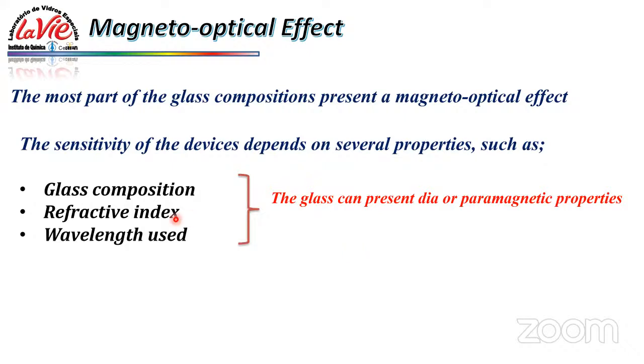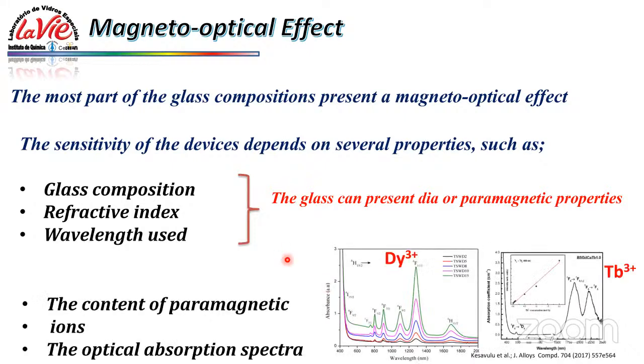We can also change the wavelength used, because the Verdet constant increases a lot with the refractive index. And how to do that? Usually when we work with glass, we can change the composition by incorporating, for example, paramagnetic ions, which can be transition metals or rare earths.